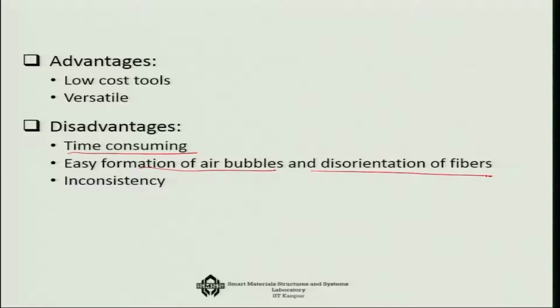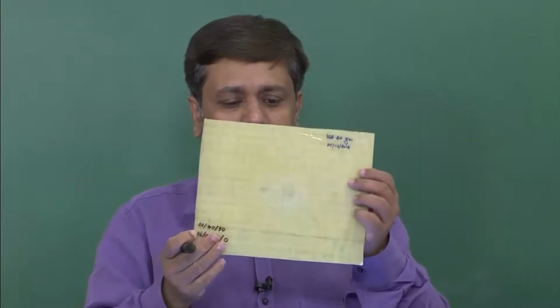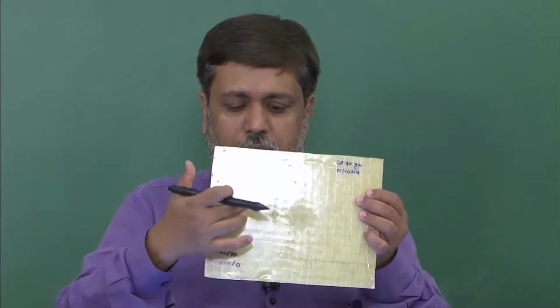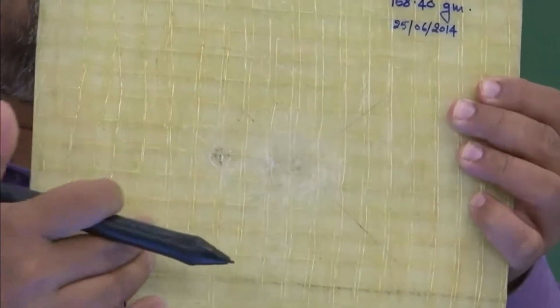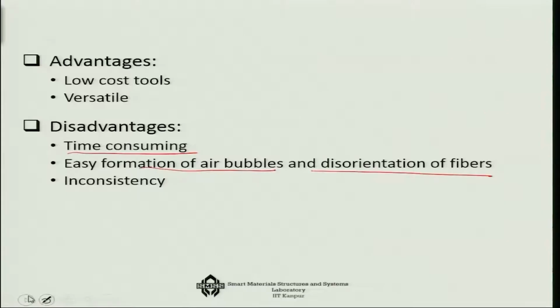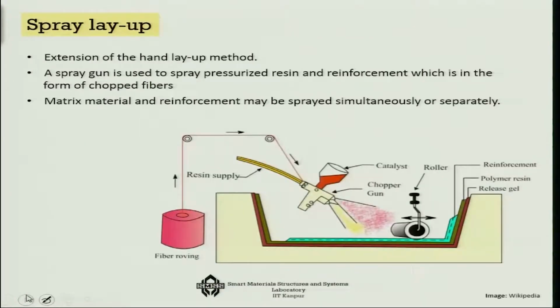If you look at this whole thing once again very carefully, you can see this disorientation of fiber. You can see that the fibers are not very straight. When you are pouring the resin, the fibers get displaced, so you do not get a homogeneous distribution of the fiber. That is another problem in the hand layup technique. Also, you cannot control the thickness very much, so there is a lot of thickness variation that can happen in the system. So that is our hand layup technique.